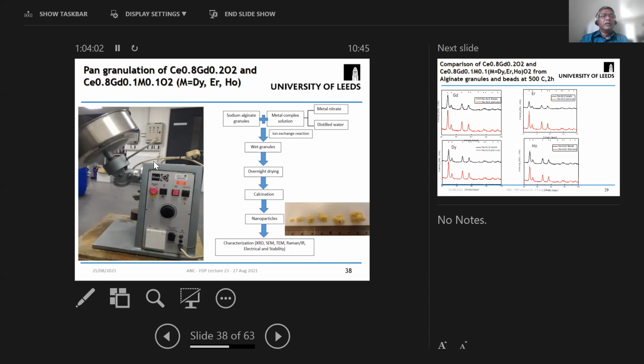So we tried to use the granulation process. Alginate powder was granulated in a pan granulator to different granules shown here at the bottom. This is the tiniest granule, and this is the largest granule. So instead of sodium alginate gel, we used sodium alginate granules, because making granules is a much easier and simpler process compared to making the beads, which is a more labor intensive process. The rest of the process remains the same. So instead of using sodium alginate gel, we have used sodium alginate granules to produce nanopowders.